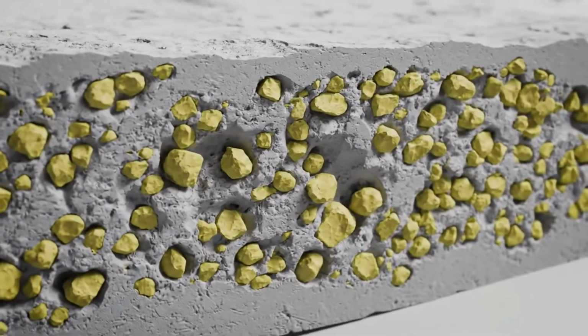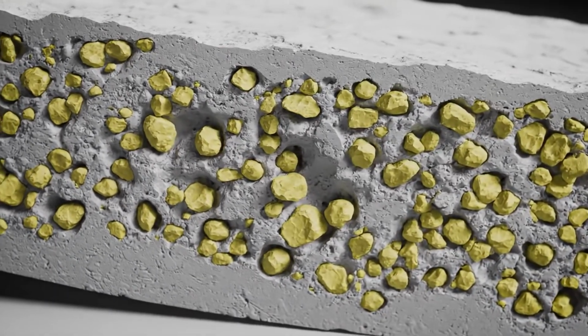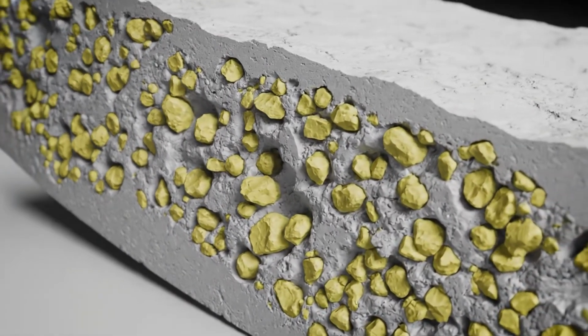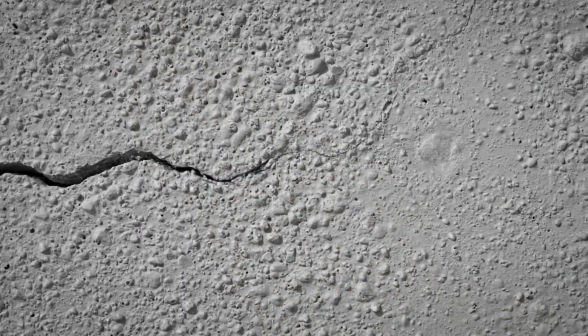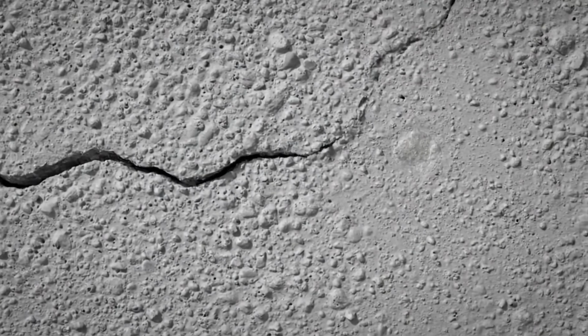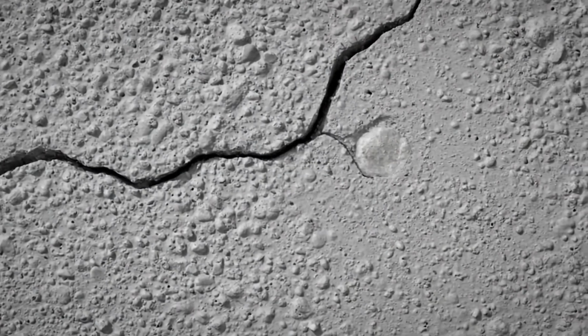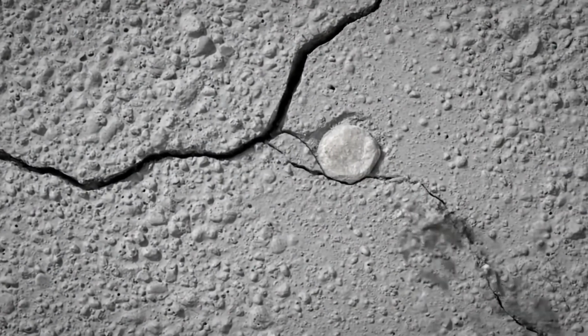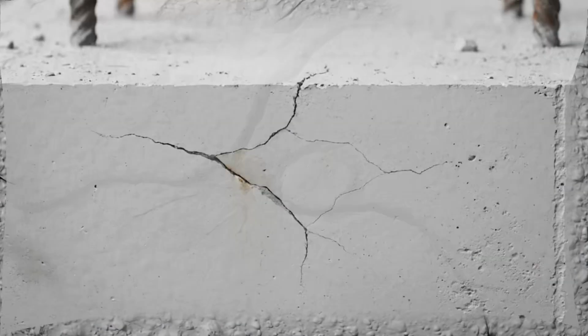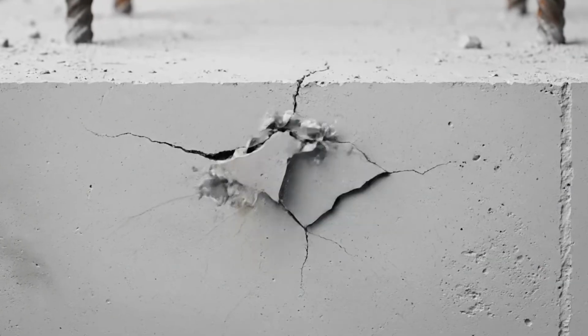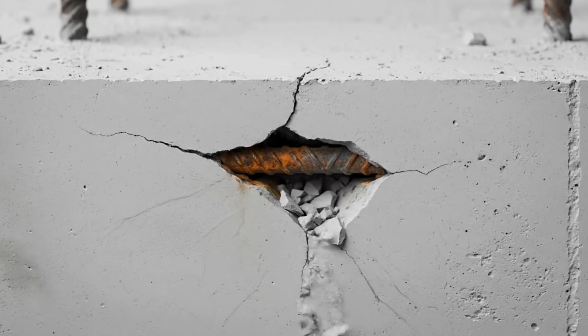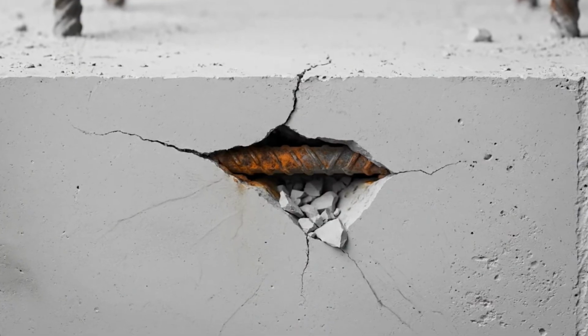It remains as lime clasts embedded in the concrete. These aren't defects, they're time-release capsules, waiting for damage. When a crack forms in modern concrete, water seeps in, the crack widens, steel reinforcement rusts and expands, the structure fails catastrophically. But when Roman concrete cracks, something extraordinary happens.